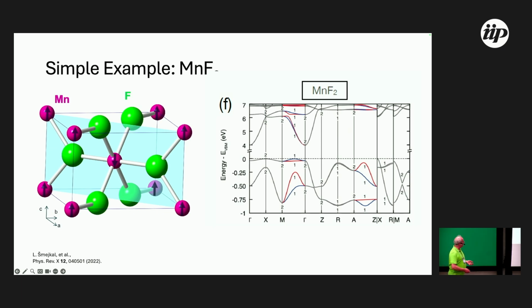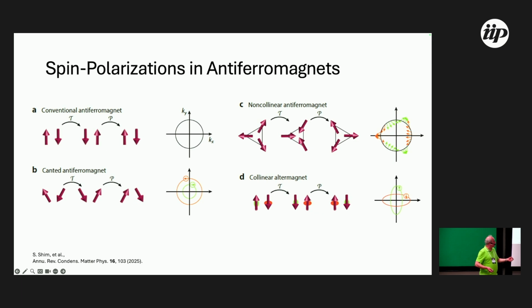Now I should say this idea of getting spin polarization in antiferromagnets can be much more general. As we said, in a conventional antiferromagnet, we don't expect anything, and this is related to the combination of time and parity together being a symmetry of the material, and therefore this Kramers degeneracy has to hold. But you can do things like cant the antiferromagnet. You can do this by applying a magnetic field. You can have a Dzyaloshinskii-Moriya interaction, so it becomes like a weak ferromagnet kind of material. In that case, you can have a spin polarization very much like in a ferromagnet because you have a net magnetic moment.